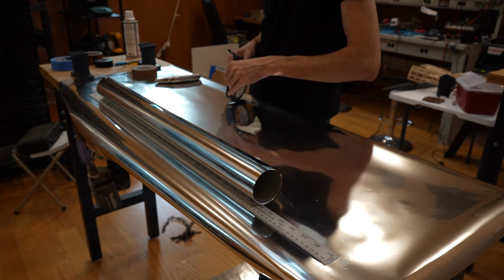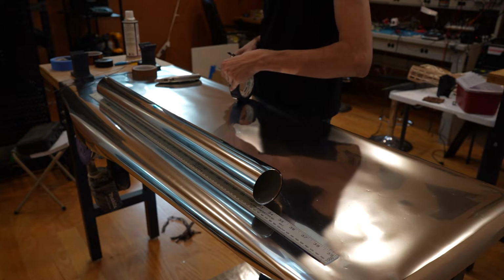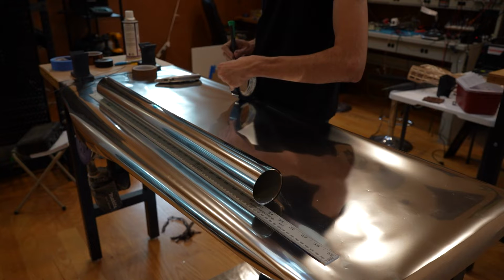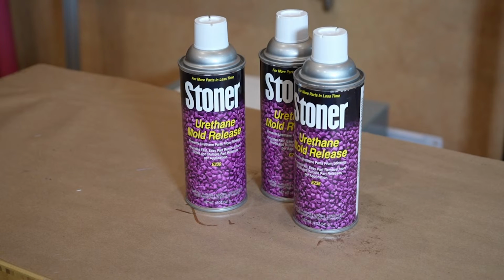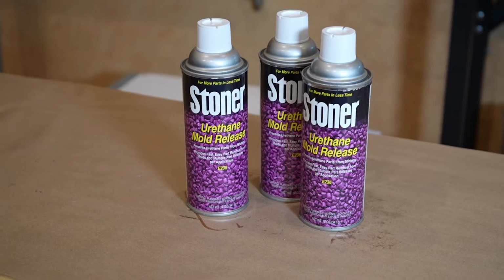Once the mylar was wrapped, I closed the seam with a layer of flash tape to prevent any epoxy from leaking under the joint and sticking to the tube. I'm not going to bond anything inside of this tube with adhesives, so I'm using Stoner E236 mold release to help release the mylar film from the inside of the tube. If I did need to bond an additional structure, I'd use E497 instead, which cleans off much nicer and allows to get a good bond surface.